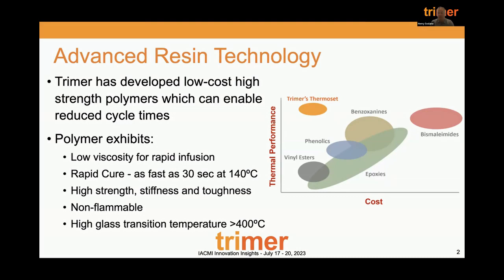Also, the polymer is innately fire resistant, and so we can generate structures out of complicated processes for fire resistant materials such as pultrusion that have quite easily met the FAR 25.853 standards for aircraft interiors or mass transit, Class A E84 rating. So really some very exciting materials. All of those properties are inherent to the material. So, aerospace properties from mechanical strength, stiffness, toughness, fire resistance of phenolics are better, very fast cure. So we can actually, I'll show you, exceed the state-of-the-art epoxies and snap cure systems and exceed what vinyl esters and polyesters can do.